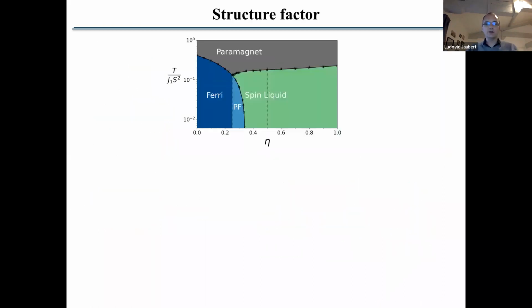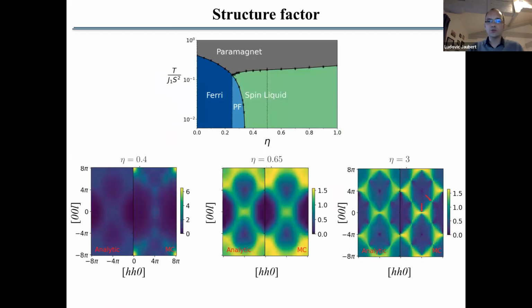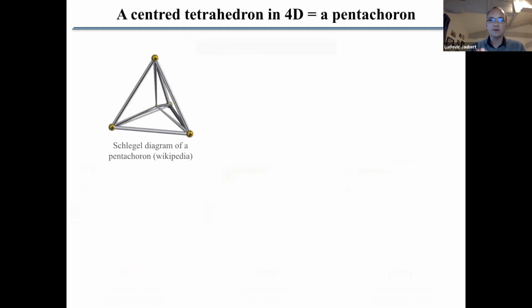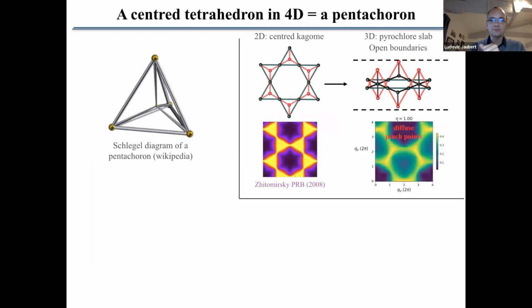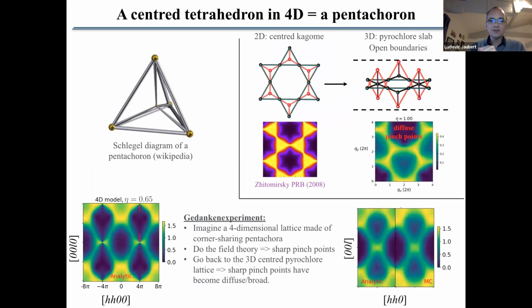And if you measure the structure factor, you can see pinch points of a 3D isotropic magnet at large values of eta, and these pinch points become more and more diffuse. I'm not going to go into the details here. I don't have time. But essentially, we can understand this diffuse pinch point that we see in the structure factor as being the fluctuations of this central spin in the centered pyrochlore lattice.